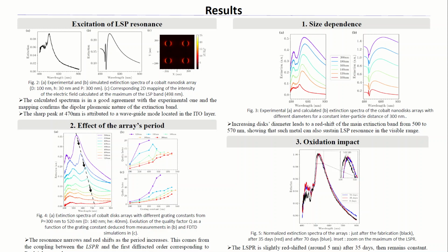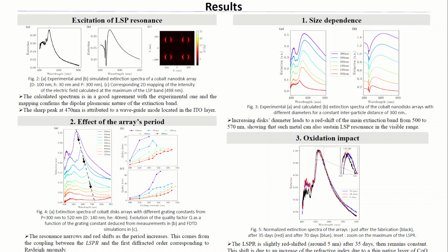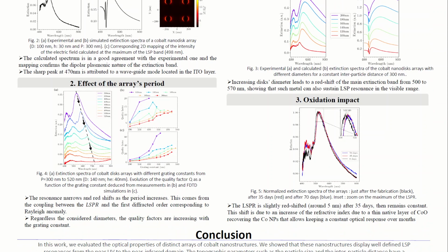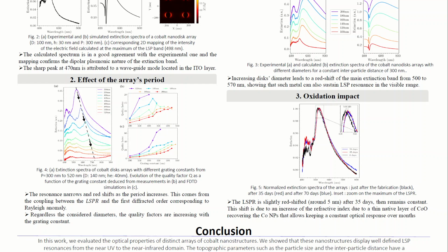So we are proposing to take advantage of the grating effect by inducing surface lattice resonance that can significantly improve the quality factor. Thus, we report that the resonance narrows and redshifts when increasing the grating constant, so we have an improvement of the quality factor. Also, the quality factor is found to be the highest when the diameters are the smallest.